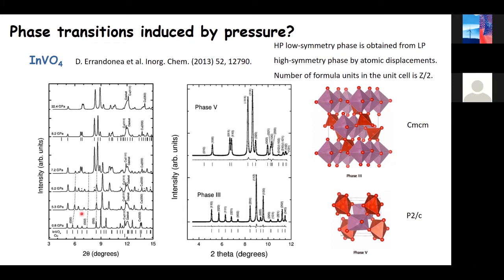Another thing we can see here is that you can compare these three peaks, which correspond to 020, 002, and 200, which move differently under pressure. That indicates that the compound has a highly anisotropic behavior. Another thing you can see is that when we compress from 8.2 to 22.4 GPa, there is no further phase transition. So we have only two phases, which I call phase 3 and phase 5, because the ambient pressure phase is already known as phase 3 in the literature. There's another phase, called phase 4, which is obtained under high pressure but also high temperature, which is different from the new phase we discovered. So the new phase, we call it phase 5. These are Rietveld refinements of the low pressure phase, showing that the structure is correct.